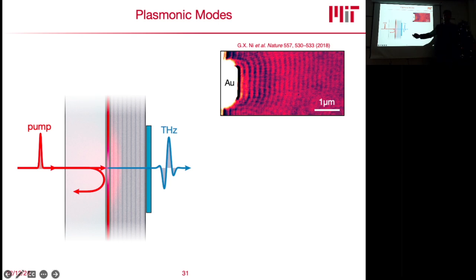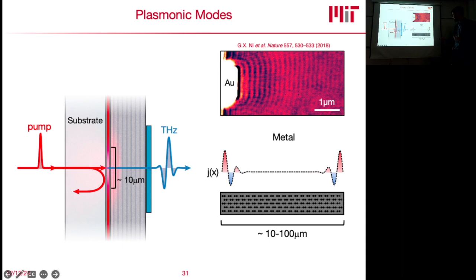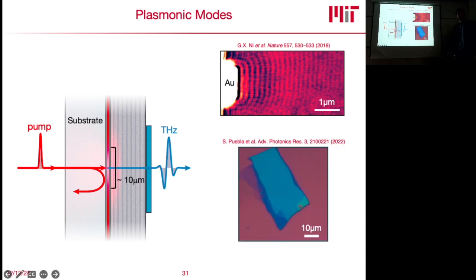This spans for like 5 millimeters, and the sample itself is on the order of tens of micrometers. So it's almost an order of magnitude smaller than the diffraction limit for our terahertz wavelength. This is not where these other people are measuring, because they have pushed it to atomic resolution. We can't do that, but we thought there's an intermediate region of micrometer resolution, which is also very important to cover. So we are looking for a situation where we can get these plasmonic resonances that they found in graphene on micrometer length scales and much higher frequencies, and bring it down to tens of micrometer wavelength